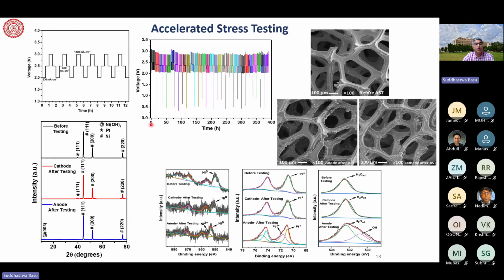So you can go for about 400 hours, there is no deterioration of the cell at all, no voltage change at constant current, and almost no corrosion or erosion taking place. We have taken out the electrode and done X-ray, with no additional peak before and after testing, at both cathode and anode. We have done XPS as well before and after testing. No change in the formulation or any deposition taking place at the cathode and anode.